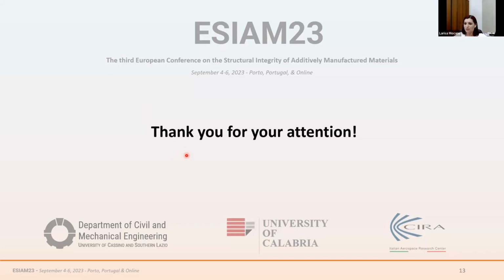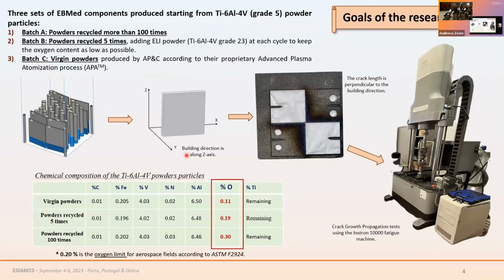Good afternoon. Congratulations for your nice work. My thought is about when you talk about 5 times of recycle. The raw material, the recycled material that you use, is it only recycled, or is there a percentage of new material? Because normally you use the recycled with new materials, and we have a percentage. Was it the case or not? For the raw material for the specimen that was 5 times, is it only recycled, or do you have both materials? Because in the recycle cycle, we put some percentage of new material and some recycled material.